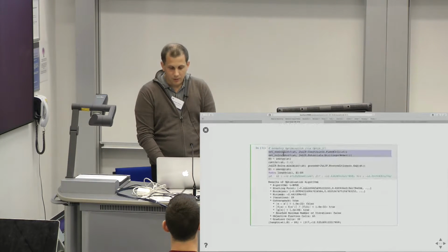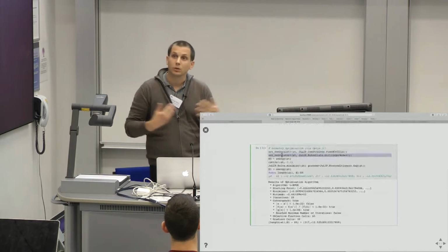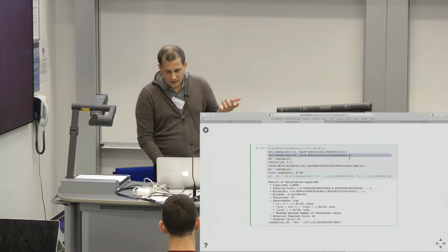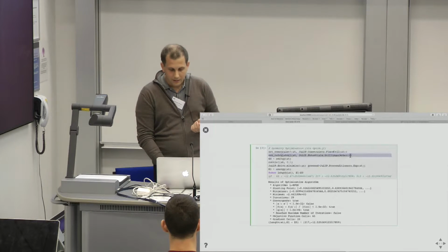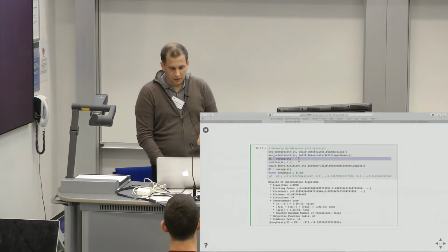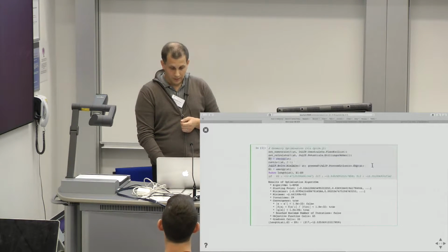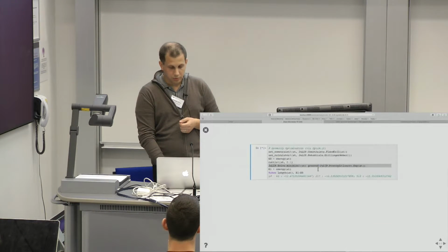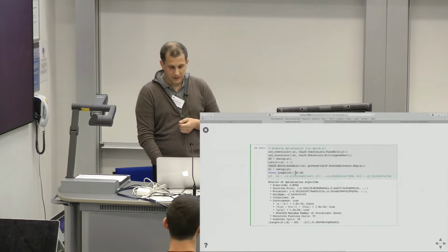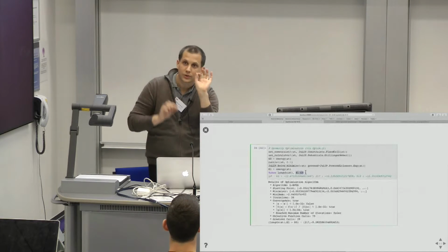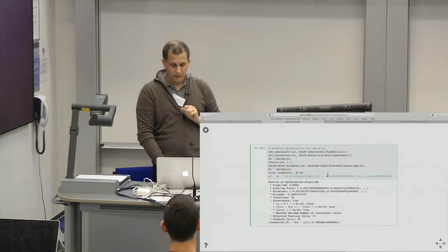I have to set up my simulation, so I have to add a model, basically. Forget the constraint, that's not important. But I have to add a model, and in this case I add the simplest model I can find, the Stillinger-Weber potential, which is what it's called. I can compute the energy, I can do other things. In particular, I can minimize. And in the end, I can output this energy difference between deformed and undeformed state, and these are the quantities that you're interested in.